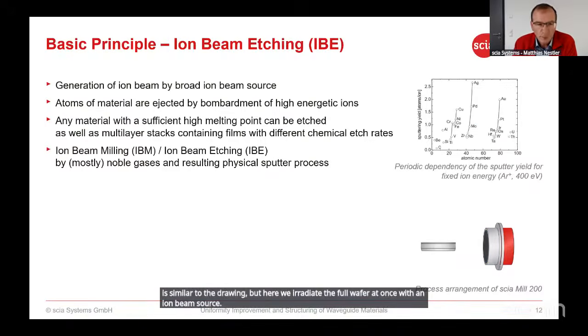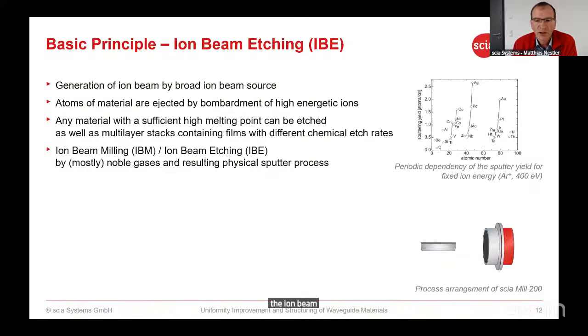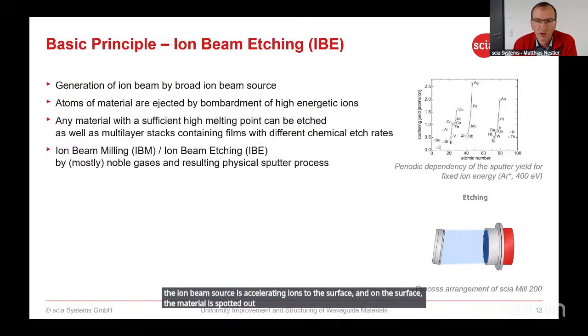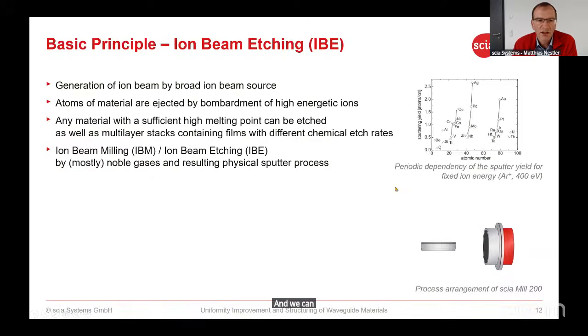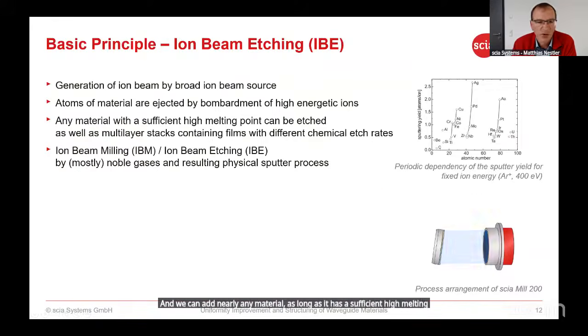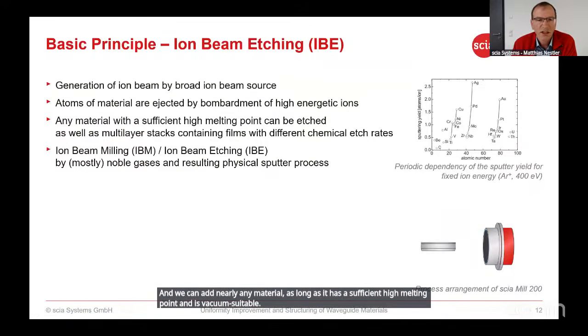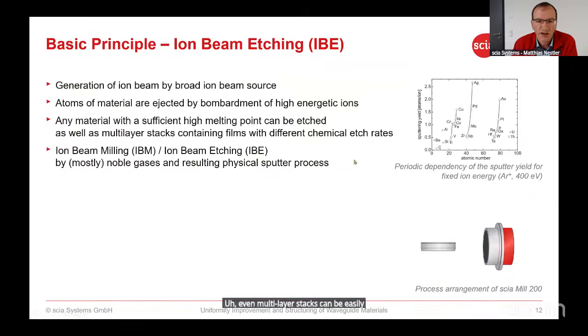The ion beam source is accelerating ions to the surface, and on the surface, the material is sputtered out, is removed, like it is shown here in this diagram on the right upper corner. And we can etch nearly any material as long as it has a sufficiently high melting point and is vacuum suitable. Even multi-layer stacks can be easily etched, since the physical etch rate is more or less in the same order of magnitude for all materials.